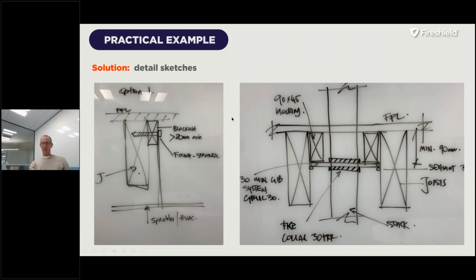Now, as part of what we did, we had to obviously, like I said before, reduce heat sinks and how we do vertical stacks. So on the left there, how did we attach, for example, sprinkler or HVAC to floor joists? Well, we introduced extra blocking and the fixing went through the blocking. We didn't want to create opportunity for fire to get in there and defeat what we were actually trying to achieve. On the right-hand side there, we had to use the GIB vertical ceiling system to allow us to get our stack through and into the floor above. But that was only in small areas, hardly noticeable, like a small bulkhead in the exposed floor, so it wasn't detrimental to the design.